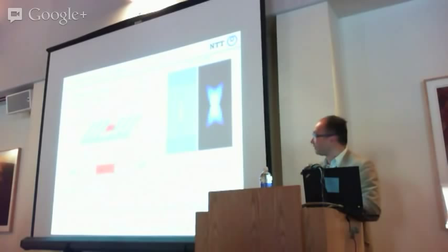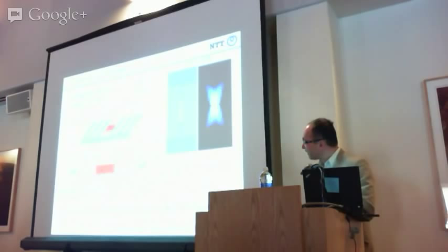To prevent the wet chemical etching when fabricating the air hole structure, the entire direction of the active region was buried with indium phosphide. This is important. And this is the calculated FDTD mode profile of the device. Since the refractive index of the active region is slightly larger than the indium phosphide region, the photon is confined without shifting the air hole. And the active volume and the mode volume are almost the same. So this means very close confinement of the photons and the carriers.